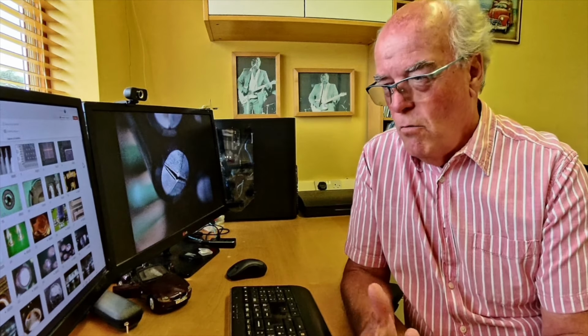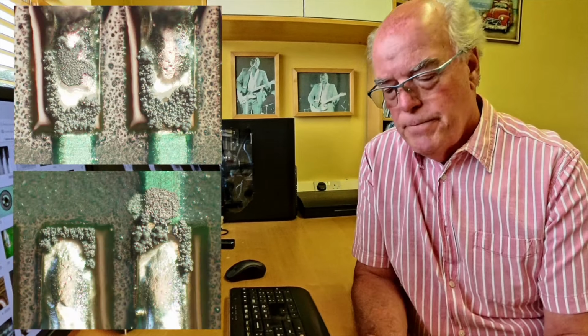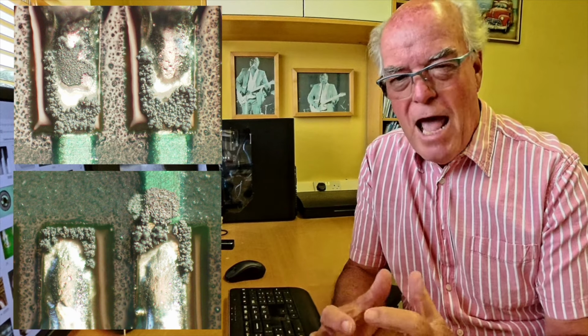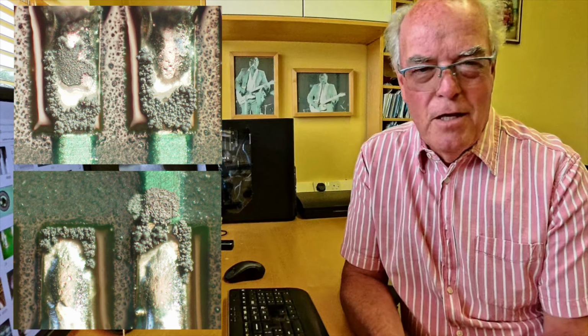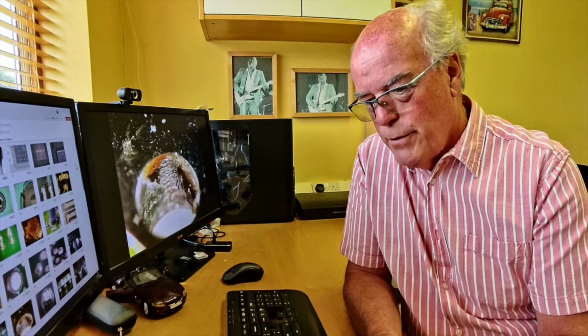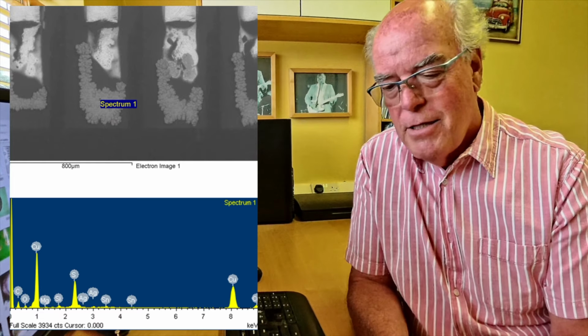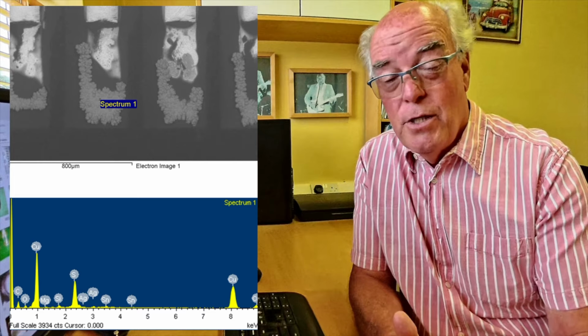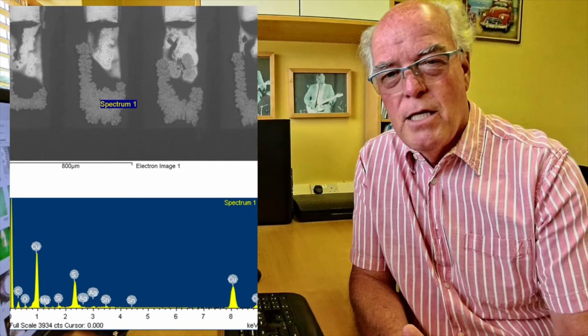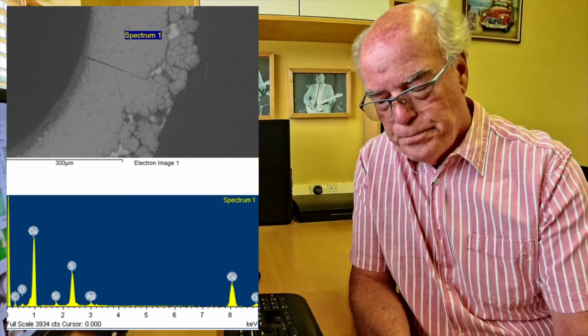If you look at high magnification of sulphur failures on boards or on termination of components, it looks like a black deposit which has a floury surface appearance, and these examples show you this type of failure on the surface of a board or a component. A laboratory can do analysis for you and determine what that deposit is, and techniques are available to allow you to do this, and then you can determine what the material is, as shown in this example.